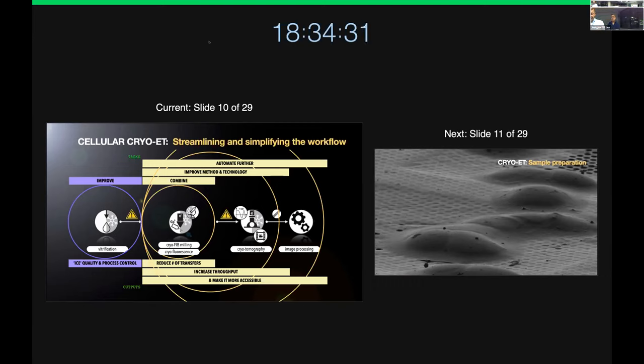Yeah. And I see directly the question Nestor has with the gallium. The gallium contamination. First of all, we checked for gallium contamination, but we couldn't detect it with the EDX detector, which we did not have on site, but off site. But in the images, you see gallium contamination, which sometimes also enhances the contrast and makes it easier for aligning the tilts of the tomography series. But how deep the gallium is going, we can only estimate at the moment. Since we are milling from shallow angles, in the range of 6 to 8 degrees, I would see it in the range of 5 nanometers